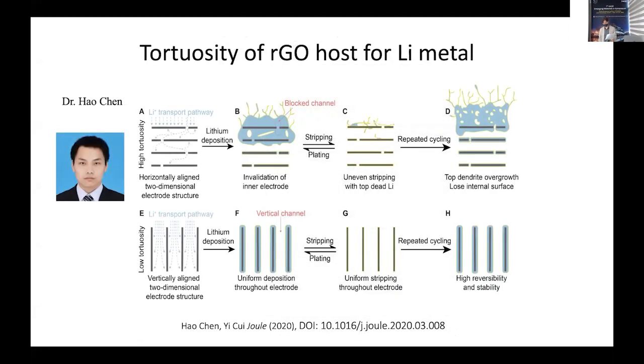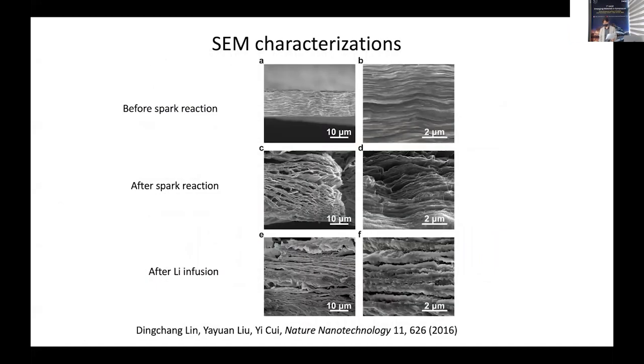So using this idea, if you imagine you do stripping, you take lithium out, as long as you have a little bit of lithium, you are going to hold the space between graphene oxide, holding the volume. So the whole volume of the graphene oxide with lithium metal composite will not change that much. If you stabilize its dimension, now you have the opportunity to build a stable SEI. So we demonstrate that there's no dendrite growth in this case.